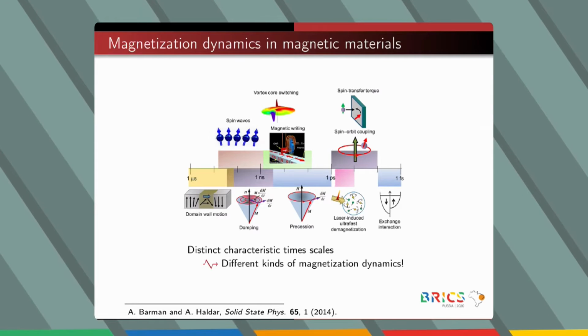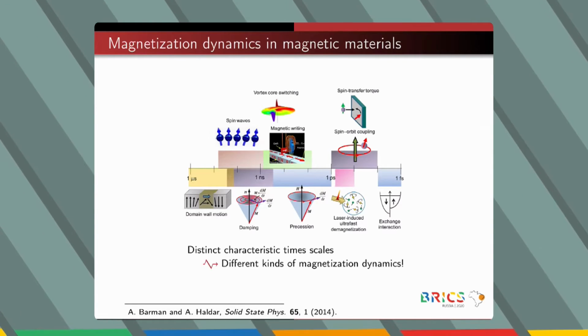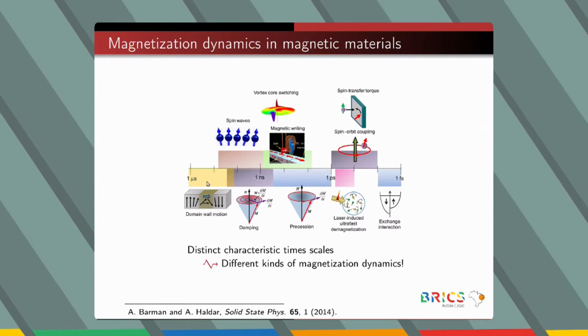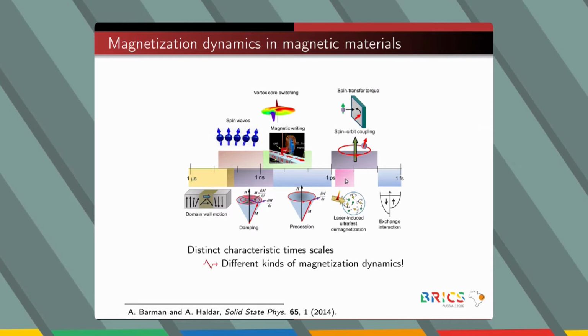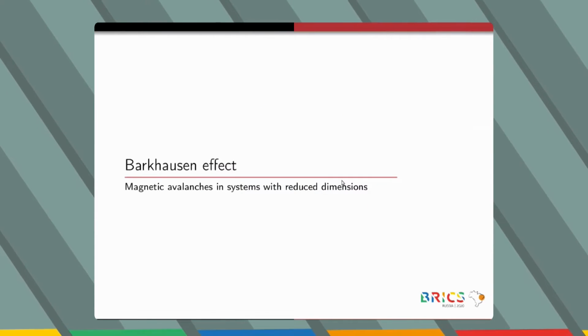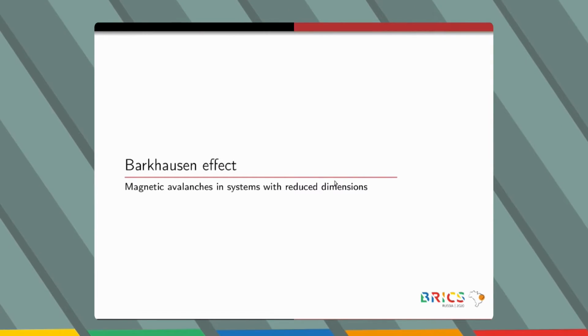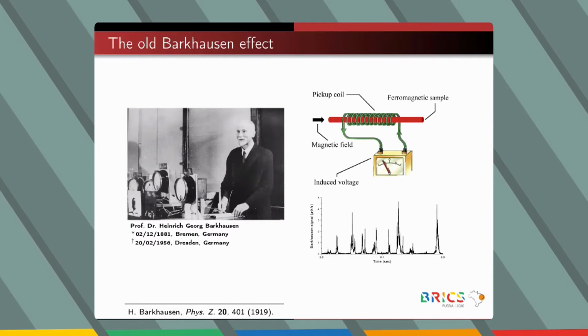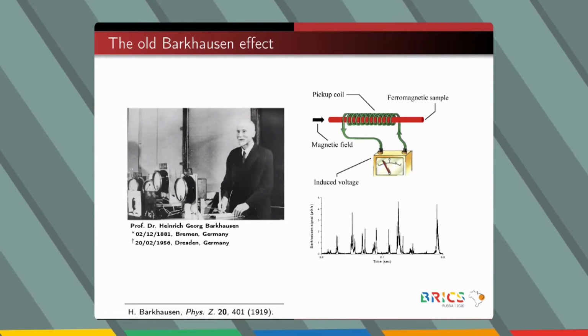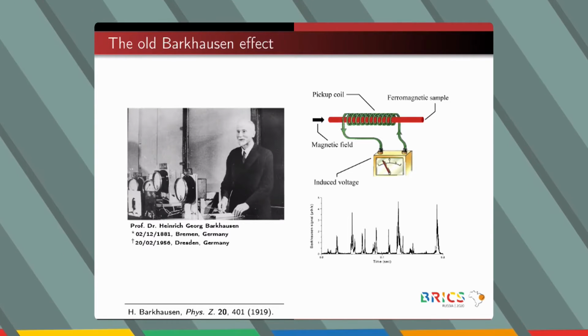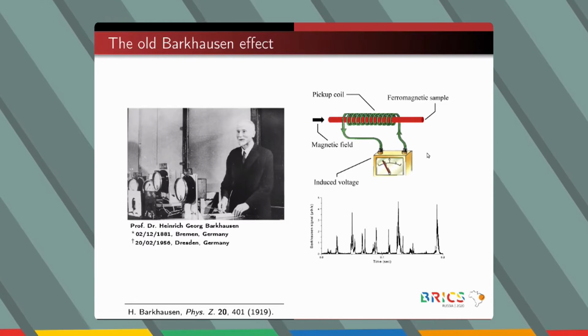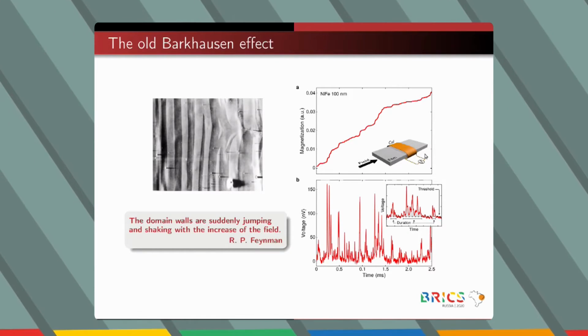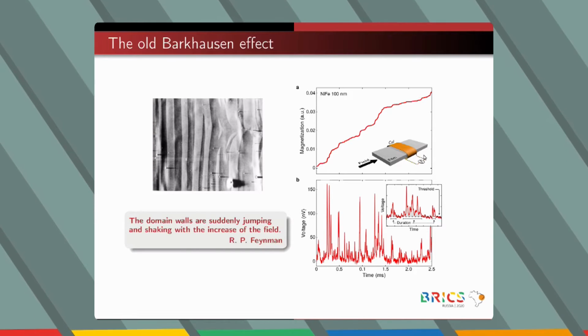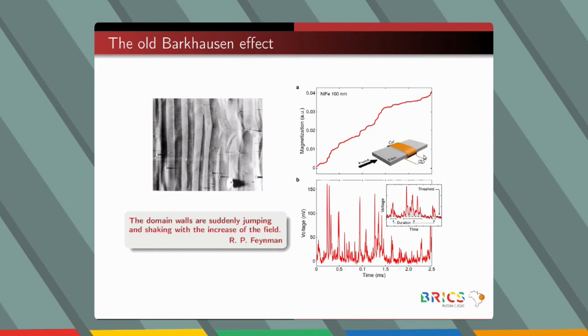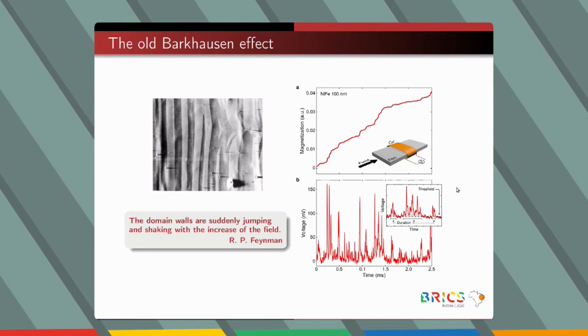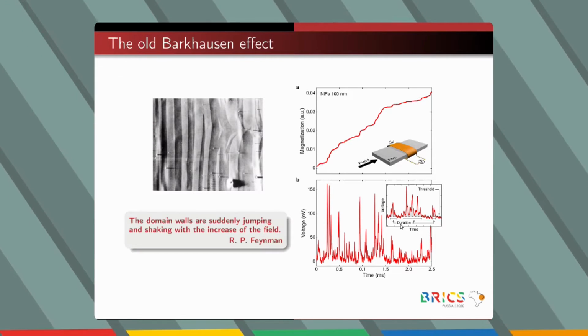Here I'm going to address two magnetic effects studied by our group, which cover from domain wall motion up to magnetization precession. The first is the Barkhausen effect, which has been the focus of my study since I was an undergraduate student. Barkhausen corresponds to the voltage pulses induced in a sensing coil wound around a ferromagnetic material submitted to a smooth, slow-varying external magnetic field. The pulses are associated to sudden changes of magnetization due to the irregular motion of the domain walls. And the noise is composed of a series of Barkhausen avalanches with a broad range of sizes and durations, which are the focus of a wide statistical analysis.